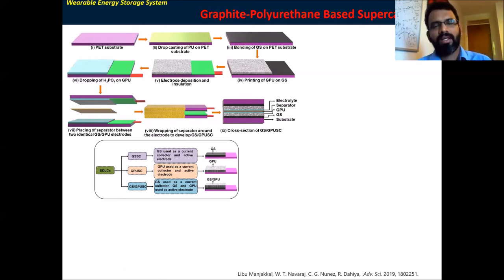But in many works, you can see aluminium foil. Why I use graphene sheet is that it can also contribute to the performance of the supercapacitor due to its electrochemical double layer performance. And then I prepared this graphite polyurethane composite. Initially, I started with different ratios. Because polyurethane is an insulative material, depending on the resistance and trade-off, I found that a 1:1 ratio gave better conductivity of this material.